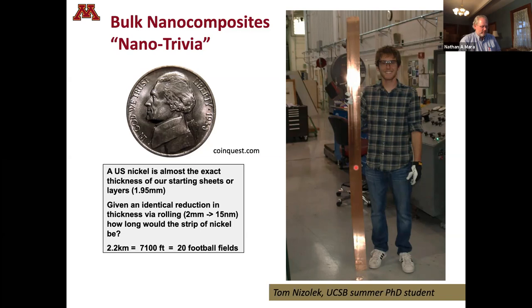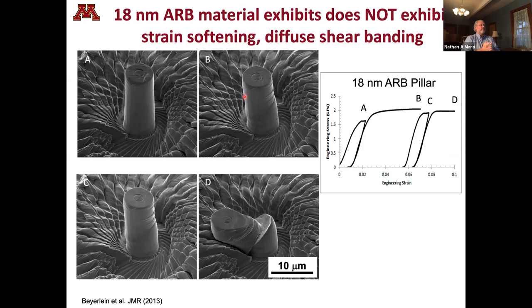So if we deform these materials, similarly to what we did with the PVD, we take a pillar, here's our pillar, and what we're gonna do is deform it in steps and take pictures. So we deform it a little bit, we get point A on the stress strain curve here. Deform a little more, we get point B. Deform a little more, we get point C. Deform it a little bit more than that, we get point D.